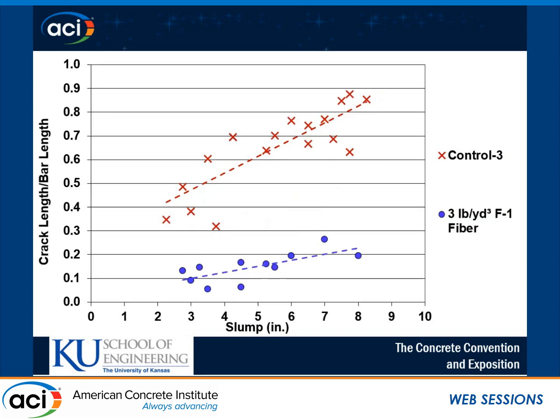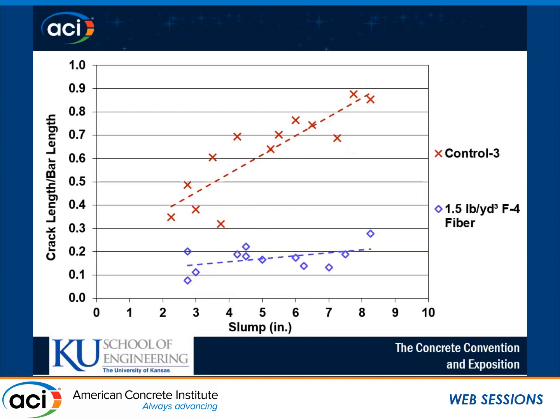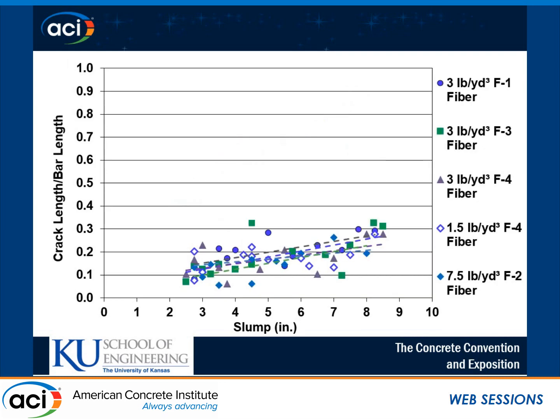Getting into our fibers, when we dosed 3 pounds per cubic yard with one of our macrofibers, we saw that for each given slump that we looked at, we had a reduction in settlement cracking. Very similar results when we used 1.5 pounds per yard of microfiber. And when we group all of our fiber results together, we see a very tight spread of data for each type and each dosage. And I'll point out that the 3 pounds and 1.5 pounds of microfiber per yard have almost the same result. The differences are not statistically significant.